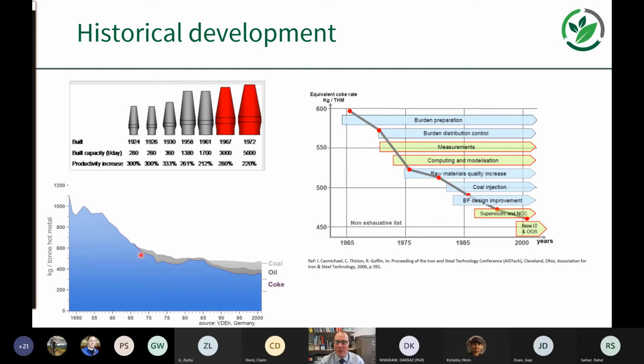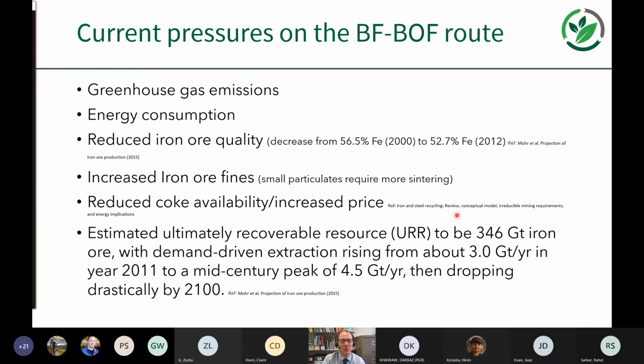We're approaching more the thermodynamic limits of the process. And then on the right-hand side, we've got technological developments in comparison with the reduction in the equivalent of the coke rate, so quite significant reductions in the amount of coke that's going into the process. And that's been an important development in improving the efficiency of the blast furnace.